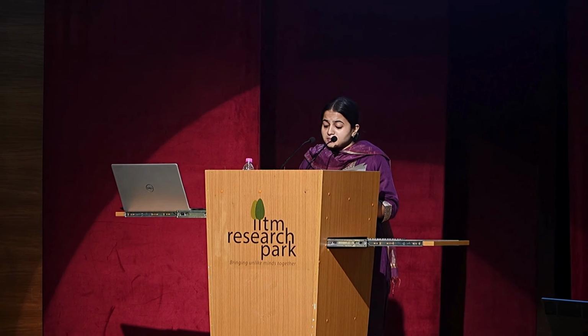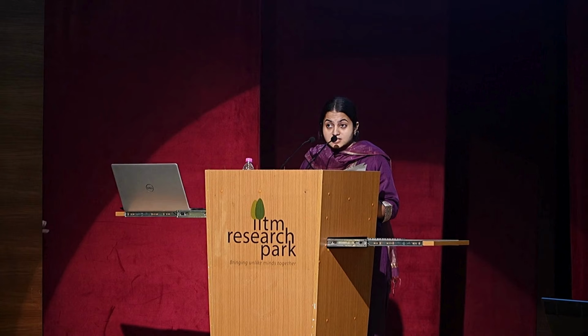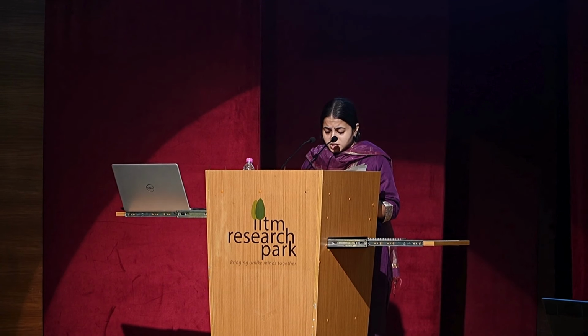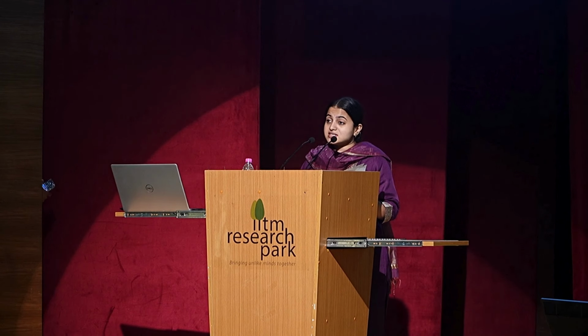Corrosion resistance in TMT rebars, a construction necessity. Rebar corrosion is the #1 cause of premature building failure. When steel rusts, it expands 6 to 8 times, cracking the concrete and creating hidden collapse risks. Corrosion is worst in high TDS water, coastal regions, and saline soils, where salts and chlorides attack rebars. The result is costly repairs, 3 to 5 times more than initial construction cost, plus visible damage like seepage, rust stains, and peeling plaster. Frequent repairs also mean higher cement and steel consumption, increasing the carbon footprint.